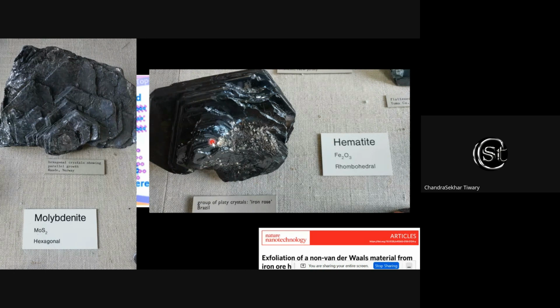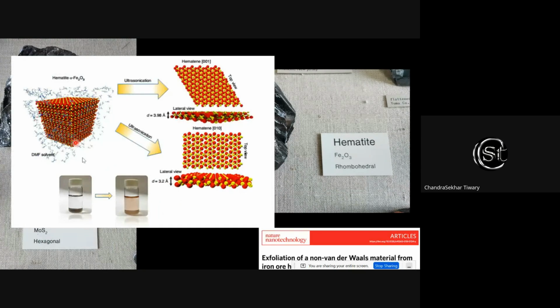So in nature, when hematite is deposited, it is deposited layer by layer, and over time the lateral grain size becomes way bigger than the interlayer spacing. Some of the spacings are separated by organic molecules or living species and so on, and hence a good anisotropy is created. Now, this anisotropy can be utilized by a small solvent chemistry where you put in a certain solvent, give energy, and they can exfoliate into atomically thin layers.